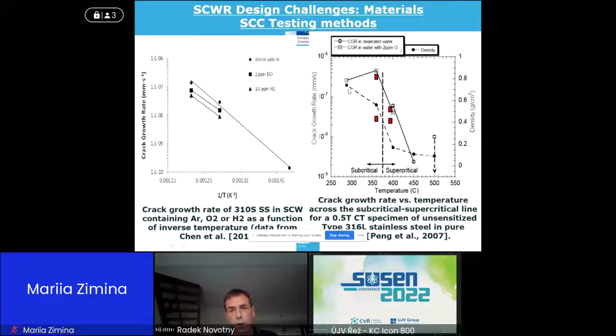And here you can see the results, and this is a very interesting study because according to the results of this study, you can see the black dots. That means the crack growth rates are reducing when we are crossing from subcritical to supercritical water. Even at 500 degrees C, a kind of saturation, it could even go lower. So in this case, it would mean that supercritical water is actually less detrimental for stress corrosion cracking.